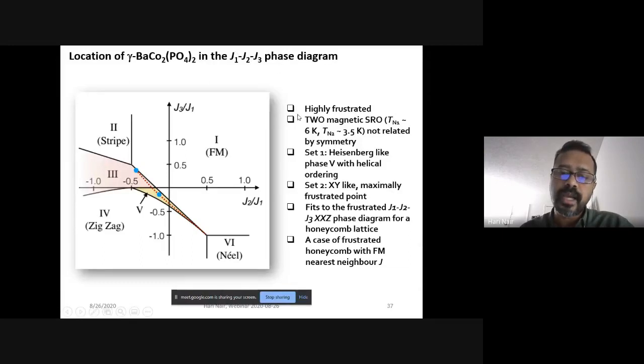Nevertheless, we have a better estimation of the location of this compound in the J1, J2 phase diagram. It actually puts it as a highly frustrated system. It is a quantum mechanical system of effective spin half, so it belongs to a highly frustrated quantum magnet with two short range ordering temperatures at 6 or 5 Kelvin and 4 or 3.5 Kelvin, and they are not related by symmetry, because one is collinear and one is helix, so they don't have a symmetry relationship between the two. So they are actually two different types of domains forming within the same material.